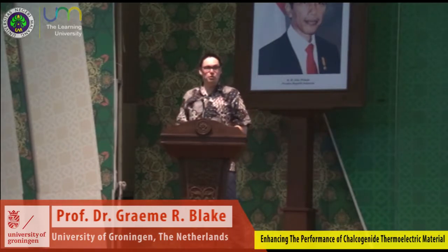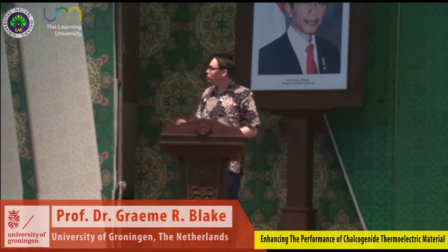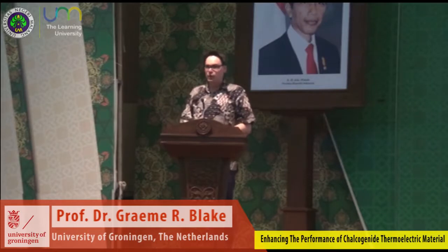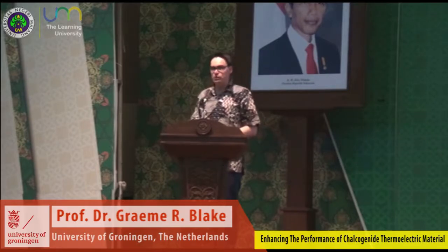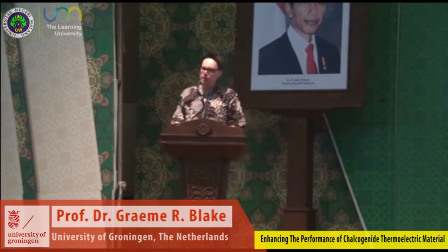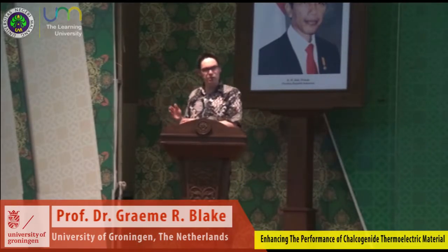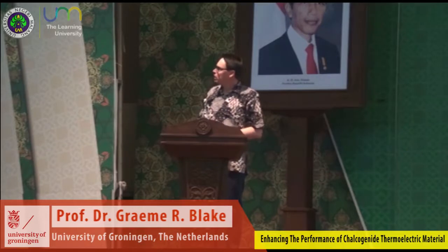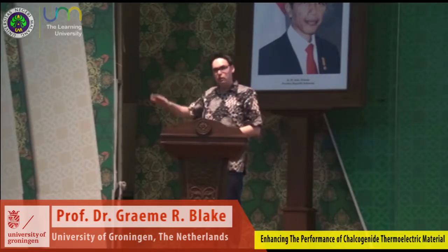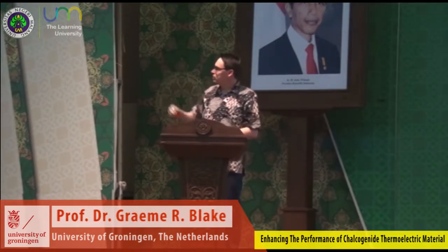And for those of you who are interested in magnetism, we've also doped with iron. And here we obtain a ferromagnetic response at room temperature at low doping levels of iron. Of course, with iron you have to be careful that the magnetic signal is not coming from the iron itself or from an impurity phase. We think that's not the case here, because this only works at very low doping levels of iron, at 1%.